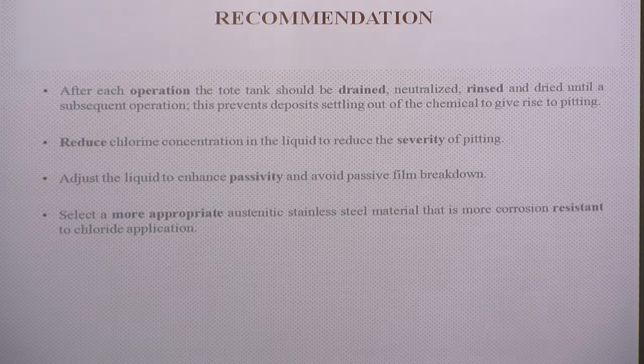Now, the recommendations for this is after each operation, the tank should be drained, neutralized, rinsed, and dried until the subsequent operation. That prevents the liquid from settling at the bottom. You can also reduce the chlorine concentration, or you can adjust the liquid to enhance the passivity. Another method is to select a more appropriate material for the chemical that you carry.